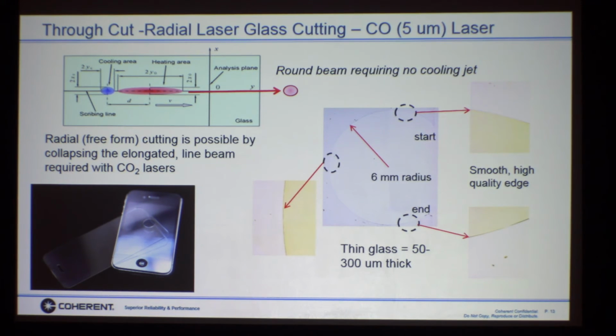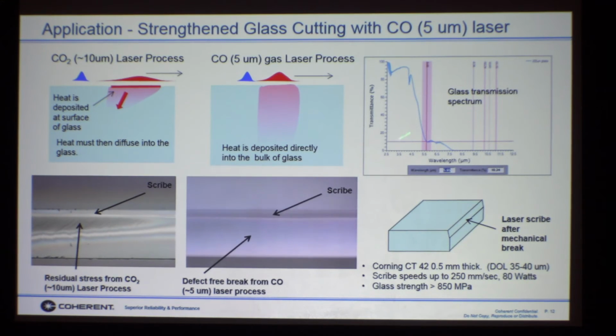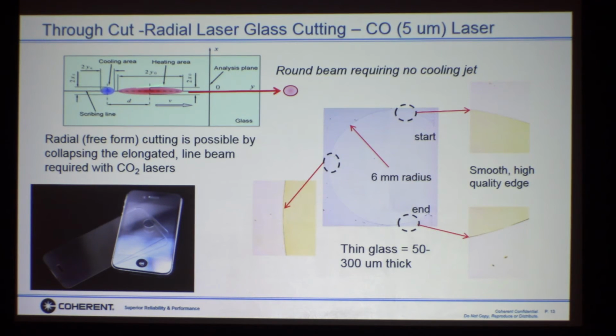So again, with glass cutting, since the 5 micron light from the CO laser isn't as strongly absorbed, we don't necessarily have to create a line the way we do with CO2. This represents the line that's created by CO2, and then there's the cooling jet behind that. Because the CO laser deposits the light directly into the bulk, we can change that line into a circle. And now that circle can do radial cuts. You see here, these are some radial cuts that we did on fairly thin glass that are through cuts in this case. So basically you're taking a circular saw and turning it into a jigsaw. Big advantage of not having super high absorption.